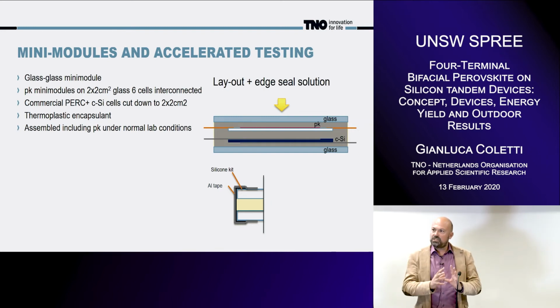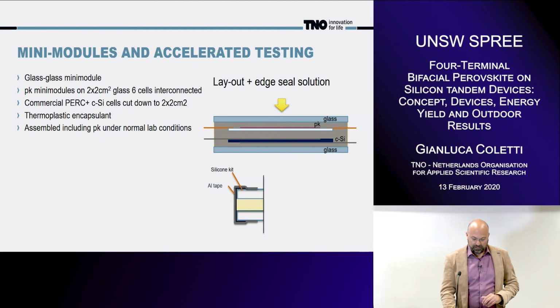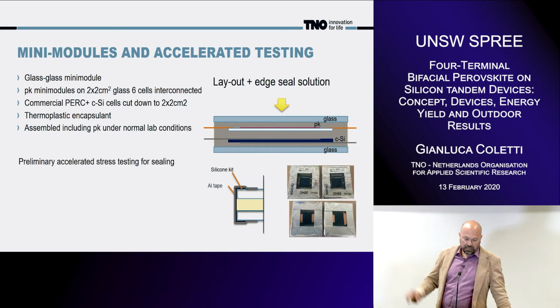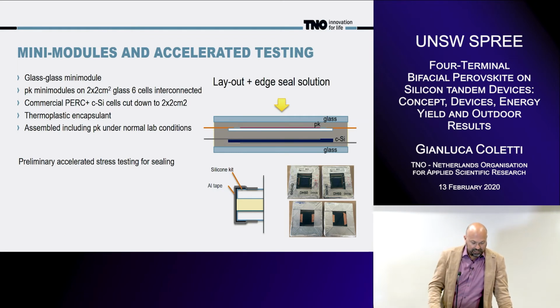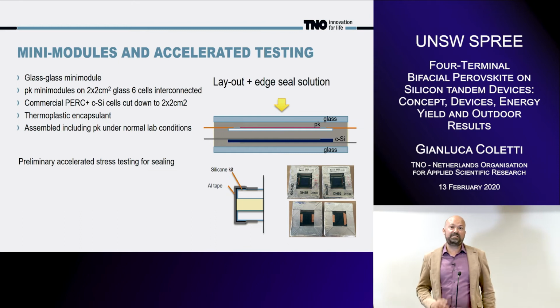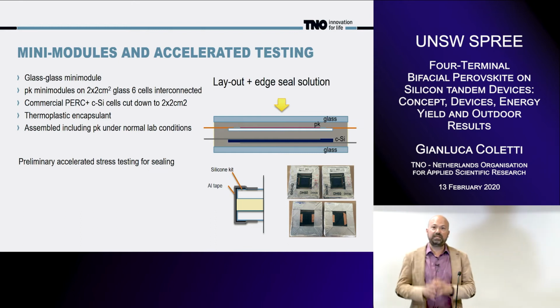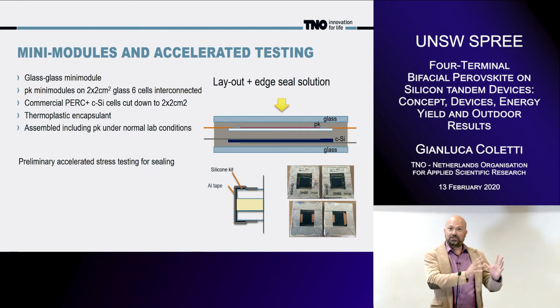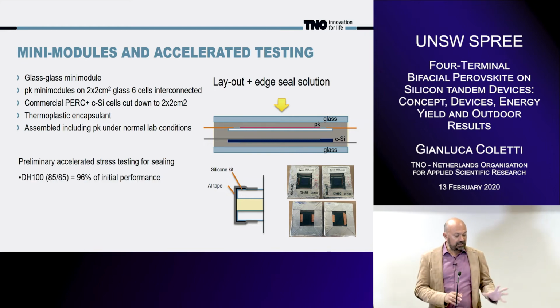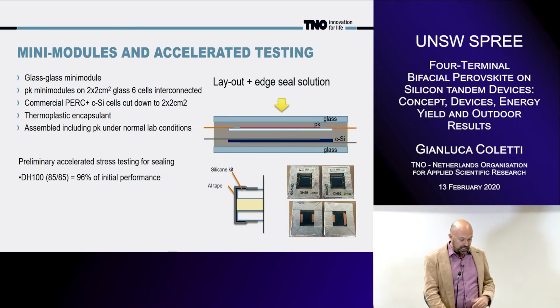And we think in this configuration, we should be able to put the device outdoor. But before we do that, this is how the mini modules look like. Before we do that, we wanted to do some preliminary accelerated tests, again, to confirm that this device will last enough time on the roof to be measured. So we start with the damp heat 1000 hours at 85, and we get 96% of the initial performance.